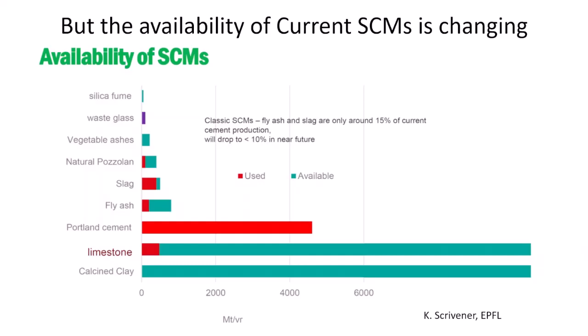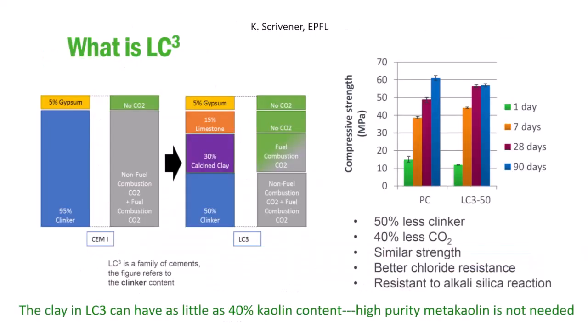So what's available for these people if we're not going to have more coal-burning power plants, and the blast furnaces are being converted into electric arc furnaces, so the amount of that blast furnace slag will reduce in availability over time. And you can do all these things people talk about, I'll talk about these other standards. They're relatively small proportions. So what's available is raw limestone and clay that can be calcined. It doesn't have to be high quality clay. You can blend them together and replace, as Mary showed, 50% of the cement. This is the same graphic she showed: 50% less clinker, about 40% less CO2, just using a different pozzolan.